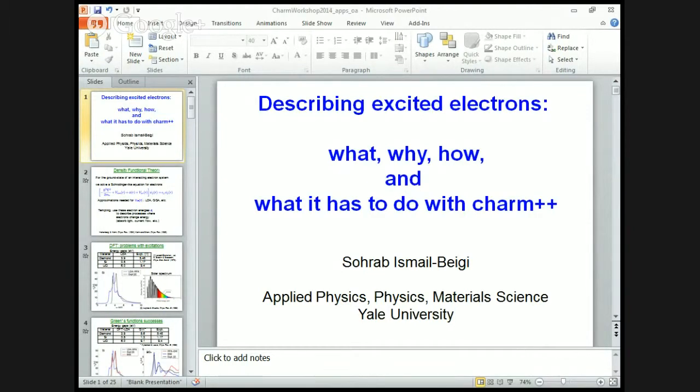So let's say you go ahead and use this kind of theory to calculate the absorption spectrum of silicon. Like, as a function of the light frequency, again in electron volts, this is a mathematical thing called the dielectric function, but it's just optical absorption. The black curve is real silicon, so it absorbs starting at 3.5 eV. And the blue one is what this theory predicts. So first of all, it predicts it at lower energy, and second of all, the shape of the absorption is different versus frequency. You might say, oh, okay, 2 or 3. Here's a solar spectrum, okay?